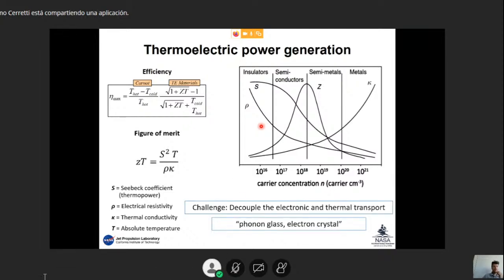So the main challenge for material scientists like myself, to improve the ZT of thermoelectric materials, is being able to decouple the two contributions: on one side, the electronic contribution with the Seebeck and the electrical resistivity, and on the other side, the thermal transport with the thermal conductivity, in order to achieve what has been defined as a phonon glass electron crystal material. So a material that is a very poor thermal conductor like a glass, but at the same time an extremely good conductor of electricity like a crystal.